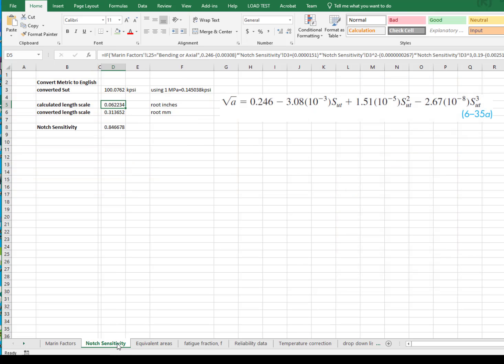So let's go to the notch sensitivity tab and take a quick look at it. This equation right here is the Neuber length scale equation for axial or bending loading, and it requires my ultimate tensile strength to be measured in kpsi. So if my units, you see that when I click on cell D, if my units are metric, then I'm going to use a conversion factor on the metric ultimate tensile strength to convert it to kpsi. If the ultimate is measured in MPa, I multiply by 0.145038 to convert that metric ultimate tensile strength, which was given in MPa, to units of kpsi. Once I've done that conversion, then I can calculate my Neuber length scale using equation 635.